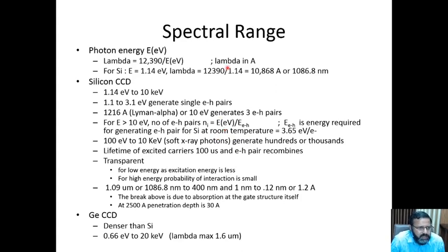So CCDs are developed using silicon for optical and X-ray region. So silicon requires an energy of 1.14 electron volt, which corresponds to a lambda of 1.086 micron. So this is the limiting lambda. Beyond this, there is no photoelectric effect.